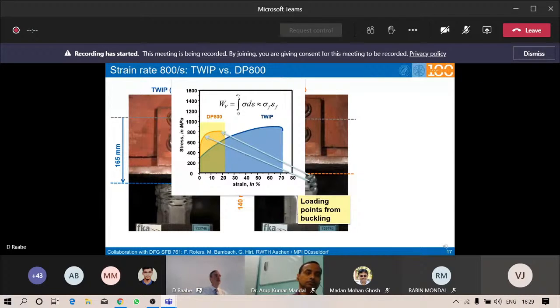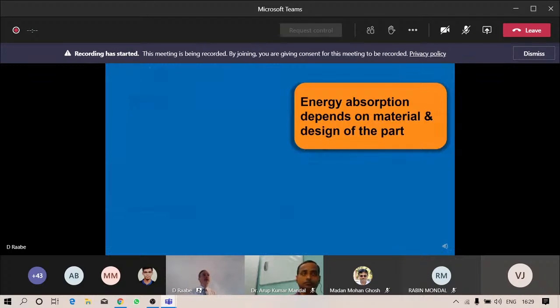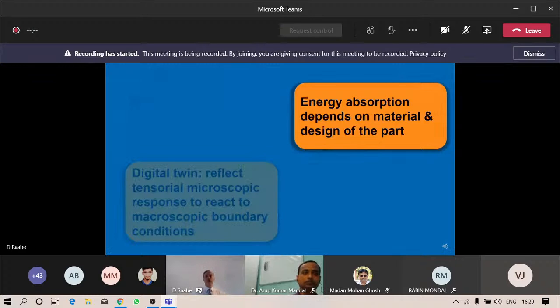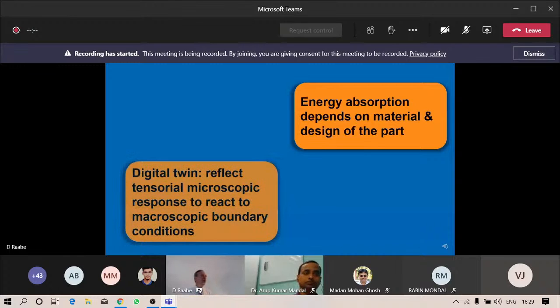That is quite trivial for a mechanical engineer, but the message here is that the energy absorption depends, of course, not only on the specific alloy you use, but of course on the nature of the part and on the loading scenario. And that means you learn here also that any digital twin or a simulation method that brings together microstructure and mechanics must be tensorial in its response and account for the tensorial nature of the loading scenario, hence must include the texture and the orientation-dependent parts of the microstructure.